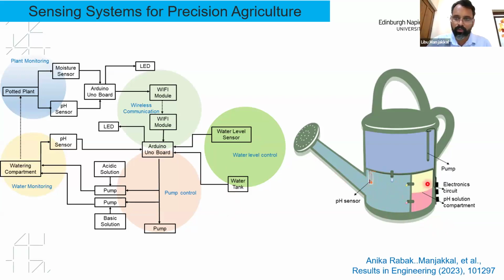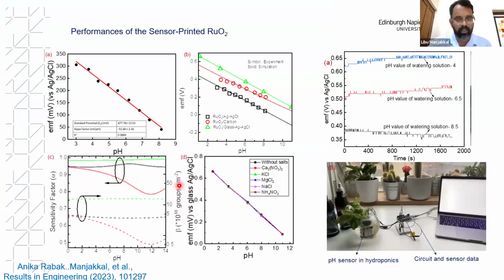And for that, you have an automated pump system here, and then a pH mixing solution, for example, an acidic solution or a basic solution. So depending on the pH required to pour on the soil, you can mix the water content and then pour it in, and then you can monitor the pH, and also you can measure the humidity level of the soil. So this is one of the systems we developed, and then we analyzed the pH in different conditions. For example, we also monitored the potentiometric performance of the sensor in the water or in the soil, as you can see from the result here.